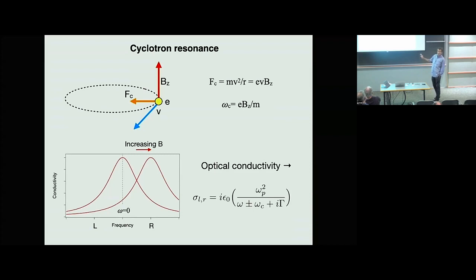We actually measure in terms of linearly polarized light, but then we can transform into whatever basis we like. And I'm going to represent left and right as positive frequencies and negative frequencies in this fashion. It turns out to be a very convenient way to do it. One of the reasons it's convenient is that our familiar Drude expression, in x and y coordinates, is very complicated in field, but in right and left coordinates, it's super simple. You just shift the Drude peak to omega c, the cyclotron frequency. That's at the level of the Drude theory.